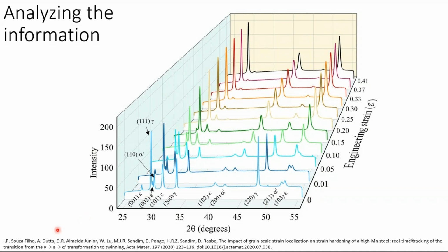In this case, this is a study of Souza Filho. The 2 theta, or the diffractograms, are in function of the engineering strain. And then let's focus on, for example, the austenite, this peak. In the beginning of the experiment, this peak is a big one. But when you are straining your material, making plastic deformation of your material, you can see that this peak is disappearing until you can't really see any peak. However, when you focus on the martensite, this alpha prime martensite, you are going to see that it starts very small, and at the end is a large peak. So you can see that from this graph.